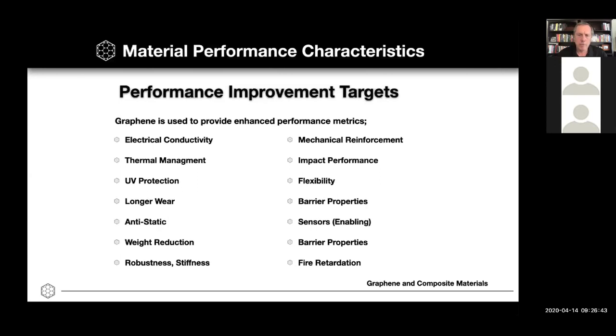And in the case of the polyurethane product for the mining industry, the intent was reduced wear on the parts, but what they found is that it imparted fire retardation on the material, which was important because when they were working on some of this mining equipment, it's a harsh environment. You often do welding, and if it came in contact with some of the plastics, it could set the gear on fire. So the fire retardation was not the target performance factor, but it was one of the happy accidents that came out of using it. It's because graphene has such multifunctionality that that occurred. And so you almost always have benefits from using graphene, as opposed to sacrifices made or degradation in performance that you want.